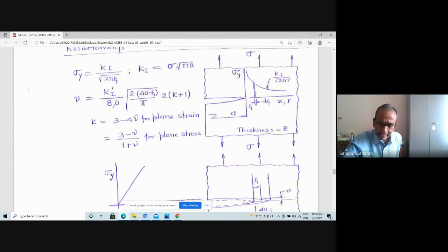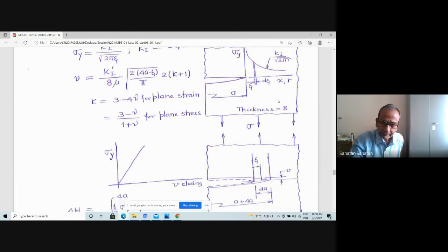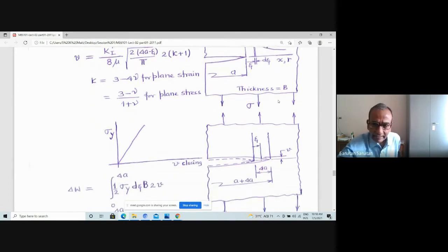And as the crack extends, look at the sketch at the bottom. Your crack was initially of size A, but now it has extended by a small distance delta A. As the crack extends, this portion from the original crack tip to the new crack tip becomes stress-free. So the opening stress on this area created by the crack extension is 0, but at the same time the crack faces have opened up.